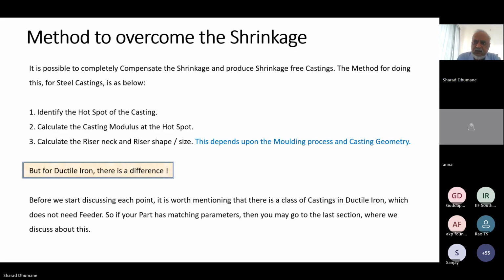So when we are doing work for steel casting, the method is to identify the hotspot of the casting, then calculate the casting modulus of the hotspot. The casting modulus is a mathematical procedure for finding out which section of the casting will solidify last, and then it directs us to give a feeder at that particular hotspot so that the feeder will completely compensate the solidification shrinkage and you get casting which is free from shrinkage defect.